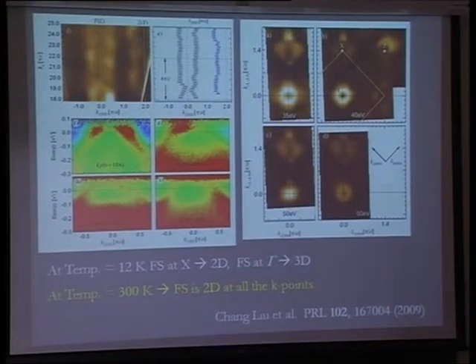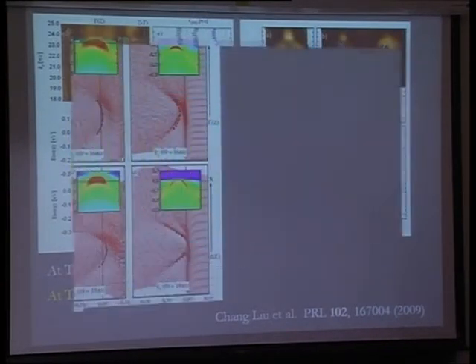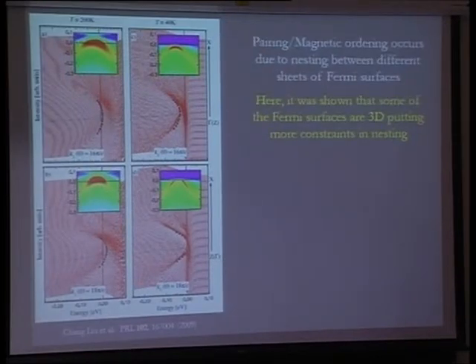That's the thing. Since this shows a spin density wave kind of transition, people think that there should be a nesting vector which is responsible for this spin density wave phase. And the nesting vector is essentially proposed to be between the Fermi surfaces at the gamma point and the X points and so on. But you can see the scenario becomes quite complicated by seeing that the dimensionality of the Fermi surface changes. This is also shown in this plot.